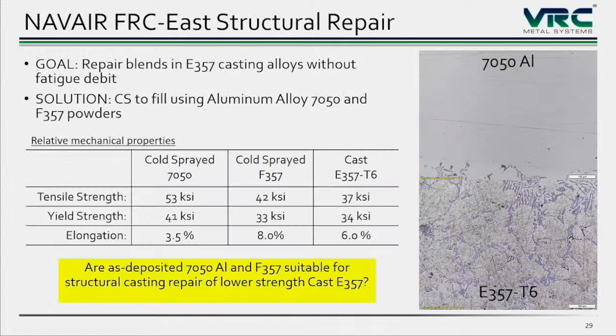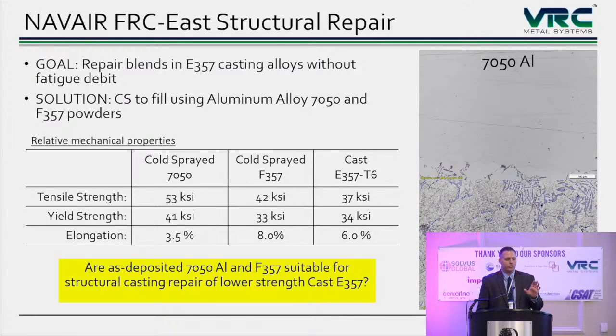So first, let's start off with some mechanical properties. I always like to get into something to do with powders and properties. The goal of this project, which was done with NavAir FRC East, was to look at E357 cast material and see if we could repair typical blends that you would see in hardware. Now, when I say repairing a blend, generally on parts, if you have a little bit of corrosion, you're allowed to do a certain amount of blending, a certain blend ratio, and that still meets the requirements of structural properties. So what we're looking at here is, can we repair that divot that was allowable and either give it additional strength or, at a minimum, no debit in strength?